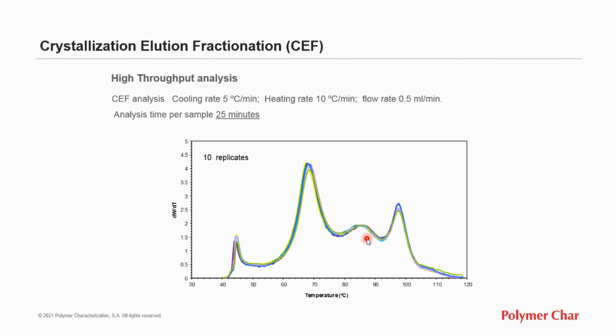But CEF can also be used as a high throughput technique, performing much faster analysis and still keeping reasonable resolution and precision. Here we see the 10 overlaid analyses of a multiple reactor polyethylene resin with only 25 minutes analysis time. So we can see clearly the resolution is good, precision is great, and the analysis time is very short. So CEF can either be used as a higher resolution or fastest technique compared to TREF.